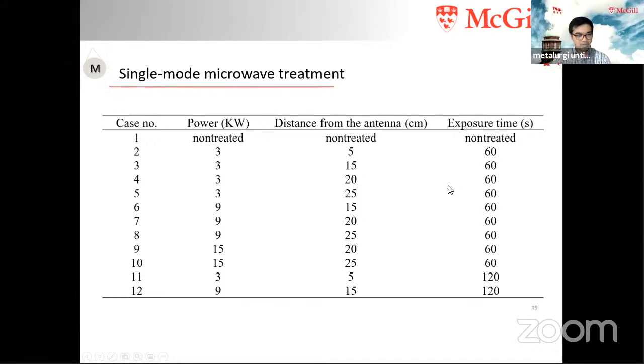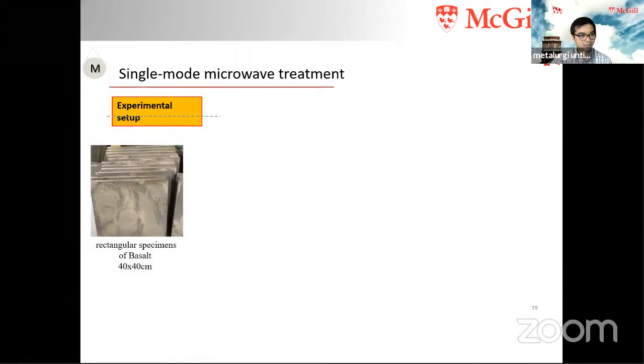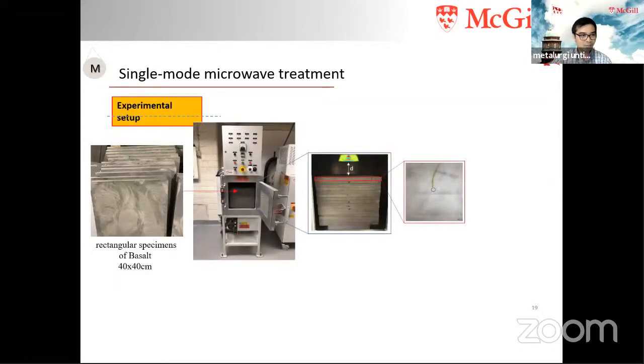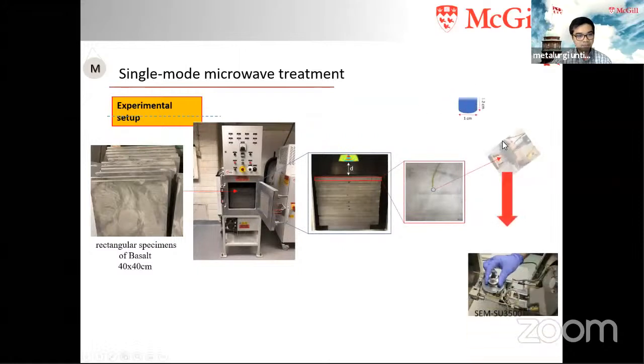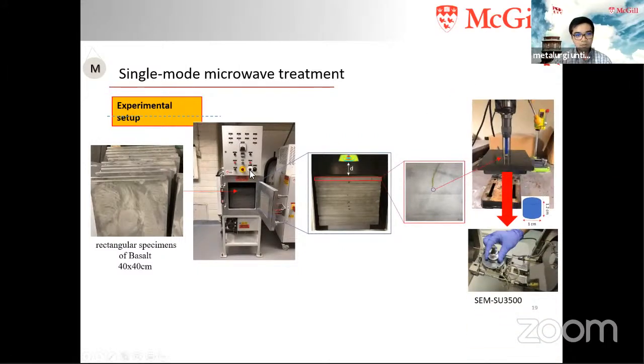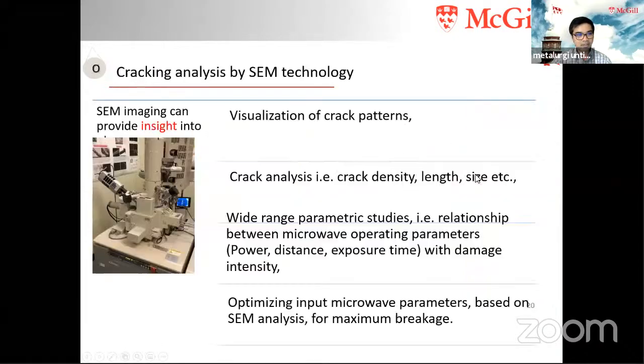In our lab, we have different microwave facilities from 3 kilowatt, 15 kilowatt, and at the moment we are building 100 kilowatt of microwave for pilot demonstration in the field. So we did some tests to microwave the rocks with different intensity, different distance from the antenna, and different exposure time. We use different types of rocks like basalt. We have some samples of kimberlite and iron ore from our industry partner as well. And then we irradiate the rocks. We characterize the cracks using SEM. We measure the crack density, the length, the size.